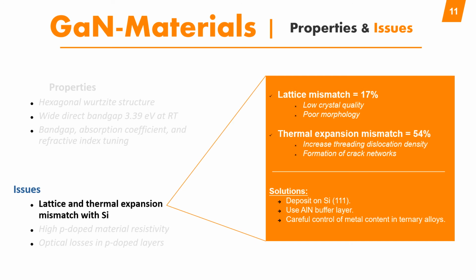So both this lattice mismatch and thermal mismatch can cause bowing and cracking in the substrate, especially for large scale substrates. Imagine an 8-inch silicon substrate, and we are depositing gallium nitride and any gallium nitride material on top of it. We could see that this high lattice mismatch and high thermal expansion coefficient mismatch can cause cracking and bowing for such an 8-inch substrate.